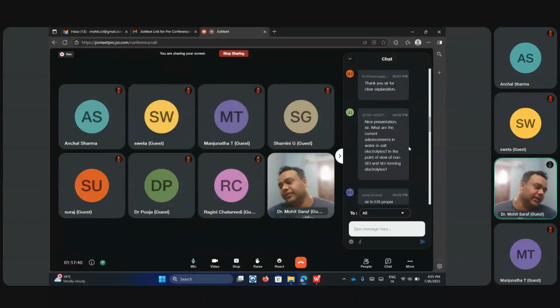Basically, this field is expanding. Water-in-salt electrolyte is a concentrated electrolyte, a very saturated kind of electrolyte, and the idea is to expand the electrochemically stable potential window. When you do this water-in-salt electrolyte, the amount of water is very low.